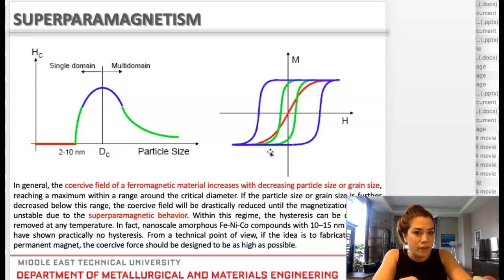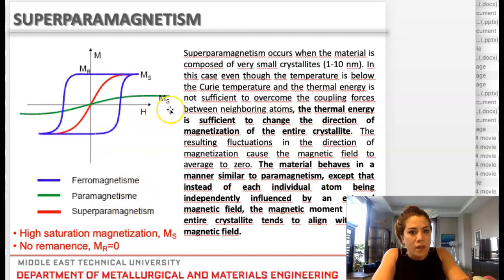But a very interesting phenomenon occurs after a certain grain size that I go down to. If I go down to a grain size on the order of 10 nanometers and below, then the material, instead of being a ferromagnet, starts to act like a paramagnet. But this paramagnetic behavior, if you compare with another paramagnet here, that will be a very, very small linear slope next to it. I don't know if I have it somewhere here. Yes, here. This green one is a regular paramagnetic behavior. But here, this red one is superparamagnetic behavior.